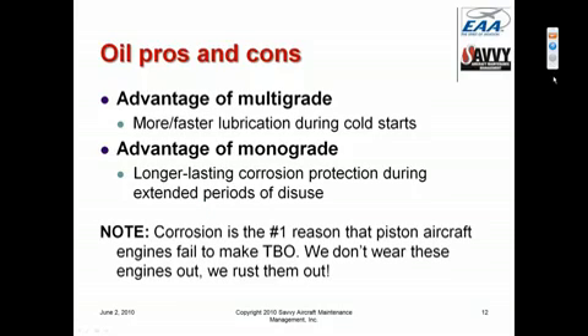With regard to multigrade versus monograde, the obvious advantage of a multigrade oil is that because it's thin at cold temperatures, oil pressure comes up faster, and we get quicker hydrodynamic lubrication when we start the engine at cold outside air temperatures. But the advantage that multigrade has for cold starting is a disadvantage when it comes to corrosion protection. Because the multigrade oil is so thin at room temperature, it tends to strip off the parts much more rapidly after we shut the engine down, and doesn't provide as long-lasting corrosion protection as monograde oil does, which is very, very thick and tends to cling for a much longer time.